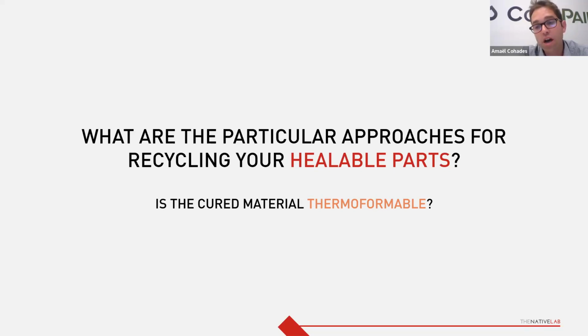Coming to thermoformability, which is different in my point of view than recycling, to some extent, yes, on specific thicknesses and at specific temperatures, the materials can move slightly. But again, don't get me wrong, the purpose of those materials, and the breakthrough behind them, is the fact that at the healing temperature, the materials are still structural. There is for sure a slight drop in mechanical properties at the healing temperature, because we are giving this ability to heal, so the material needs to move to some extent.